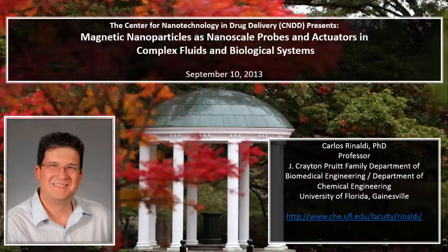But the real interesting one is going back to the first things that I showed you with the breakdown of the Stokes-Einstein equation. So to test that idea, we used linear polyethylene glycol GPC standards of different molecular weights. This is the GPC traces. We measured the viscosities. They're all Newtonian. They are melts, but the molecular weight is low enough that the entanglements are not significant. There's not a lot of non-Newtonian behavior in these systems. And then we suspended PEG-coated cobalt ferrite particles. So the particles are coated with the same polymer as the melt.